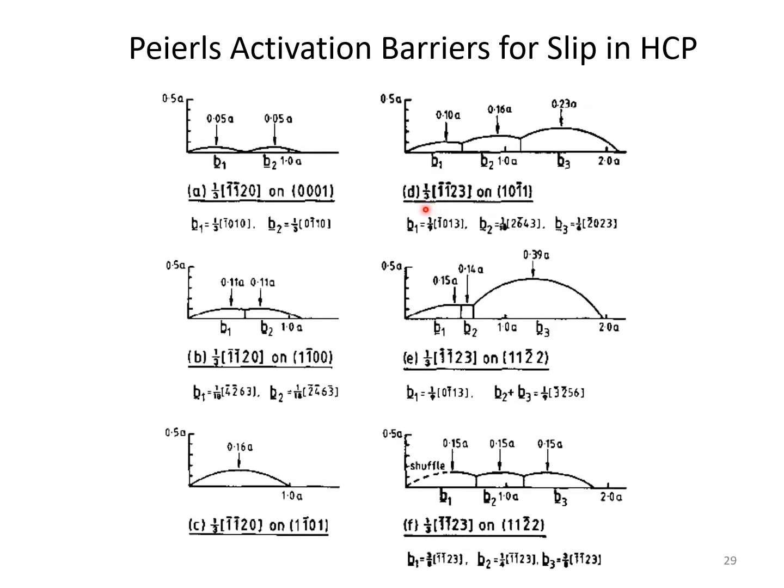If you move a distance equivalent to an A lattice parameter and a C lattice parameter, the vector that denotes that change, in letter form, is this one. It's 1/3 <11-23>. You can well understand that often when people are chatting, it's awkward to be saying, well, that's a third 11-23, or 11-21-3, or third something else. Often you just simply say C+A.